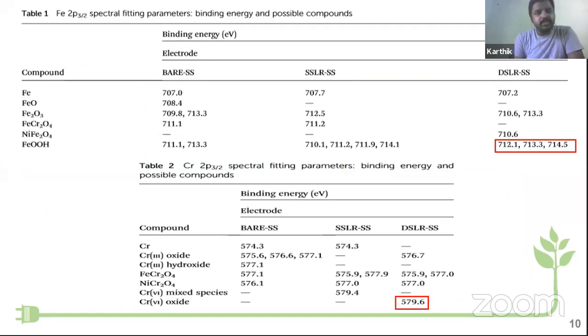Table 1 represents the Fe 2p 3/2 spectral fitting data. Here you can see the differences. The major difference is that, compared to bare stainless steel, the laser textured stainless steel possesses higher oxidized ions, that is Fe3+, Fe3+ oxyhydroxide. More three valent ions are formed over the single as well as double side laser textured stainless steel.